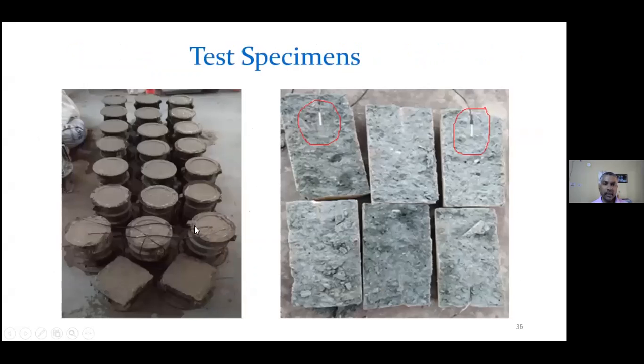3 concrete specimens from each mix are tested in the compression testing machine, the break test, at different times to know the actual compressive strength. And the other specimens give you the maturity values, as we are assessing the strength through the maturity method. The Wi-Fi microcontroller receives the data from these specimens and automatically computes the maturity indices of each mix. So you see here, this many specimens are there. 3 of them are instrumented and others are kept for the break test. So these 3 are not broken. They are kept to send the temperature data continuously up to 32 days. From this temperature data, the maturity index is calculated, and these other specimens are meant for the break test.